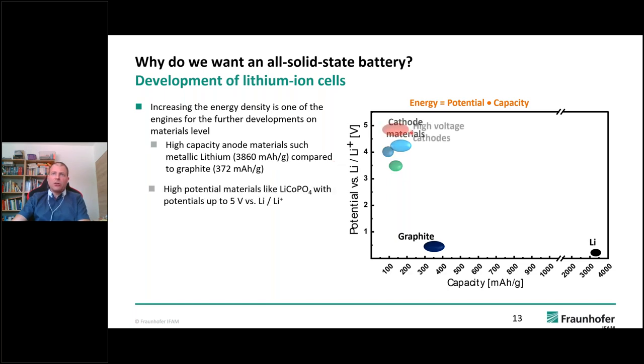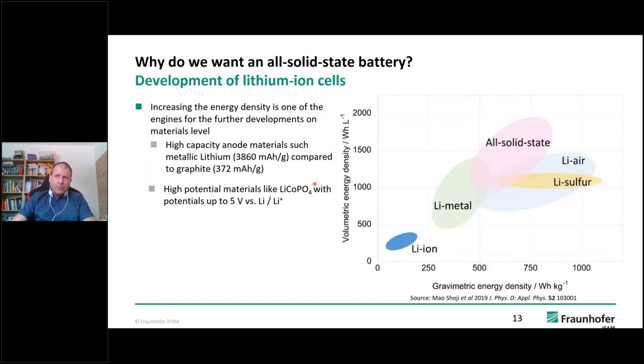On the other hand, we can also think about high voltage cathode materials going up to 5 volts, even increasing the energy by the factor of the potential. There are also already materials achieving this, but not stable enough for commercial cells at the moment. So when we take this into account, without knowing too much about the technology itself, this would lead to a very large increase of the gravimetric and the volumetric energy density.